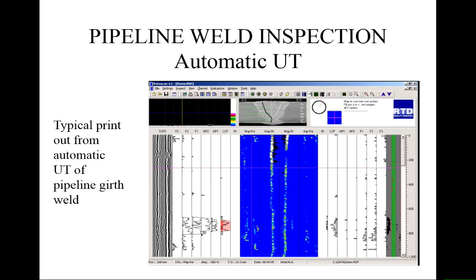So normally what you would do with these systems is have some sort of calibration, so you know what sort of signal you're looking for. So you make welds where you know there's lack of fusion, you set it up, you look for the signals that you get, and this is measuring both sides of the welds. This side is good, this side is not, and that's typical with a lack of fusion where the cart is over to one side of the preparation when you're doing these automated welds or mechanized welds. So you can get quite a lot of information.